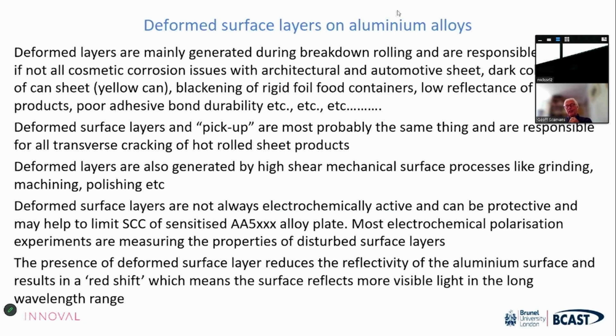So just to summarise, we now know that whenever you hit an aluminium surface with a rolling mill, hot or cold, or whether you grind the surface or machine the surface, you produce these ultra-fine grained deformed surface layers. And these deformed surface layers control many of the properties, particularly the reactive properties, the corrosion properties, the adhesive bond durability properties of aluminium surfaces. And these have an absolutely vital role in determining the behaviour of aluminium surfaces in industrial application. They're critical in architectural applications, they're critical in automotive sheet applications, they're really important in beverage cans, they're really important in blackening of rigid food containers, and they not only control the corrosion properties, they can control surface appearance, like the control of